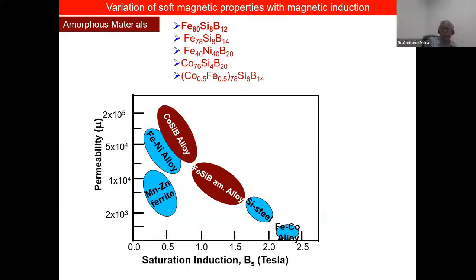So we get a set of different alloys, called iron-silicon based amorphous alloy, cobalt-silicon based amorphous alloy, and also iron-nickel-boron based amorphous alloys. And you can say that although we have compromised a little bit on saturation induction, we have the advantage of getting permeability of the order of 10 to the power 4. So you are compromising in one respect, but gaining advantage in another.